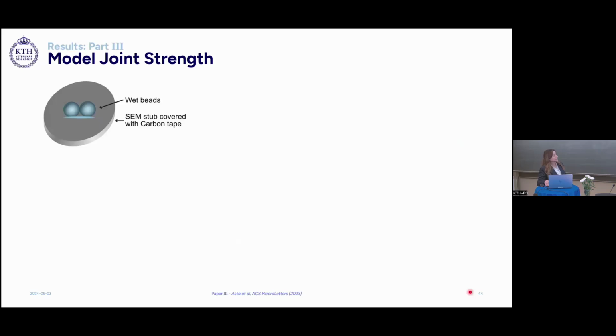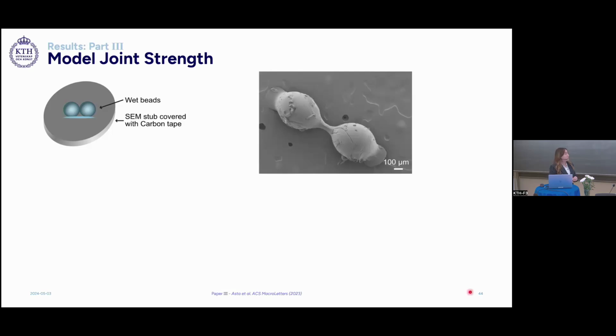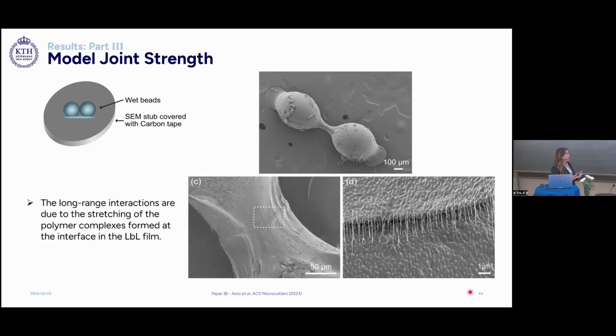To further investigate the effect of the LBLs on the surface, we dried the cellulose beads on carbon tape. Previously, when the beads are dried, they are free to move when they shrink, and therefore are able to form a more closely packed contact area. However, when they are dried on carbon tape, they are restricted from moving, and therefore when they shrink, this causes necking and stretching of the polymers at the interface. This means that the long-range interactions are due to the stretching of the polymer complexes, which are formed at the interface in the LBL film.